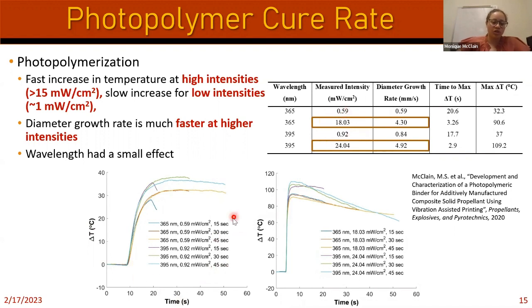So we changed the time that the light was applied for, and we measure the temperature change over time. So we could see that in general, 15 seconds is not really that long in this case. It doesn't really reach that asymptotic region that we see as we increase the time. And in general, we can see that the temperature maintains itself pretty well in the reaction. So there's not extreme cooling or anything going on there.